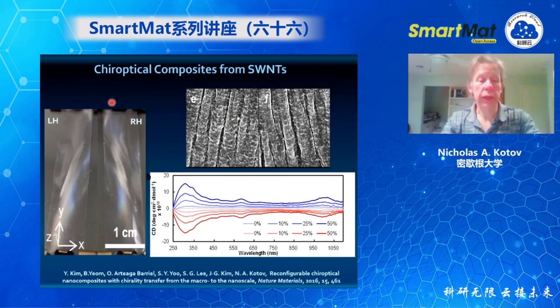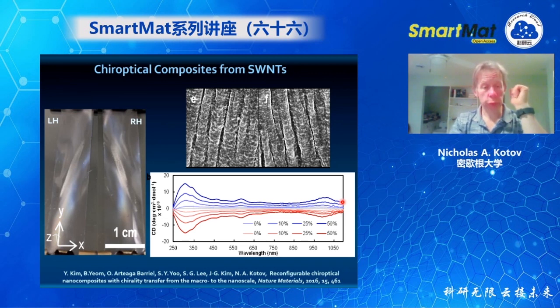optical properties. Not only that, but we can also do it with some other materials, for instance, carbon nanotubes. In this case, we chose metallic carbon nanotubes, which are also plasmonic, but in the infrared. So they have a peak in UV, they have a peak in the visible, and they have that very useful peak in the near infrared, about 1,000 nanometers. Useful for a number of reasons, and biomedical reasons are one of those. The modulation here still works, and this is identical to the mechanism that you saw with gold nanoparticles.